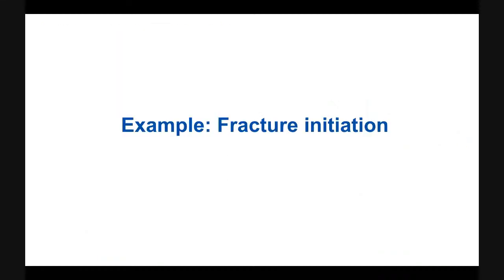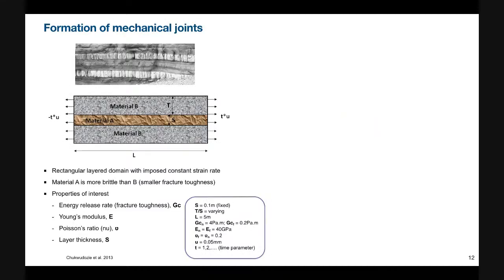So now we will look at some examples. The first example I will show here is fracture initiation. It's the formation of mechanical joints. We can find such mechanical joints in outcrop, and this is considered to be a set of tensile fractures in a brittle layer. So we constructed a simple 2D model with a weak layer in the middle. And by weak, I mean smaller fracture toughness.